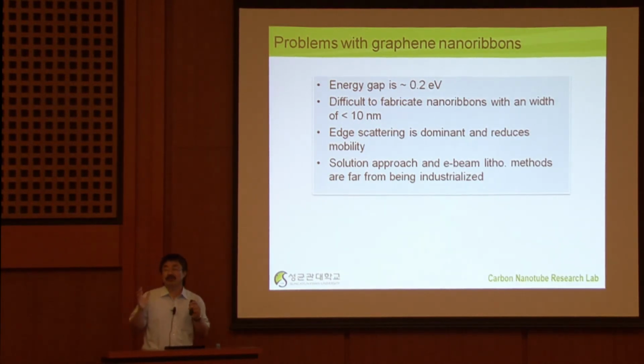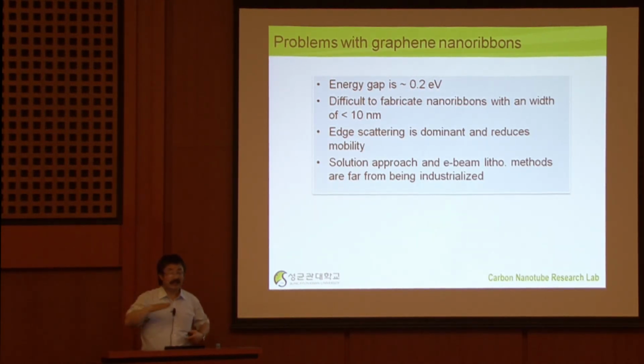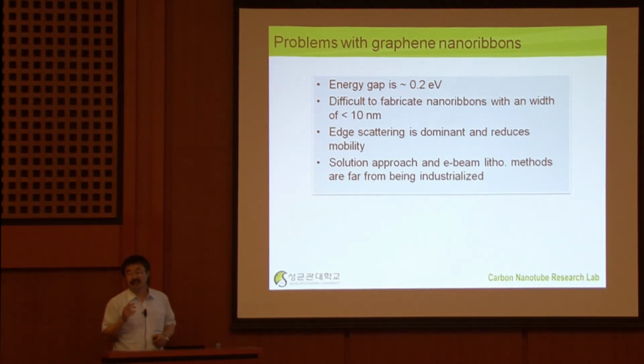But even though you are able to make a nanoribbon with less than 10 nanometer, what happens is that when an electron goes through this, the electron can be scattered easily by this edge state. Okay? So there's no guarantee you can get this high mobility anymore. So this is again the trade-off phenomenon. And we have to find some good way of making this nanoribbon without causing this edge scattering. This is an open question for all of us.